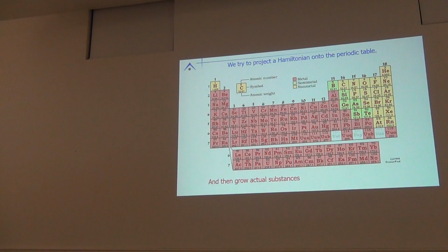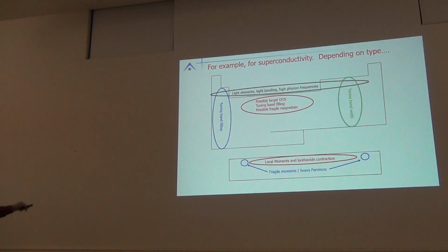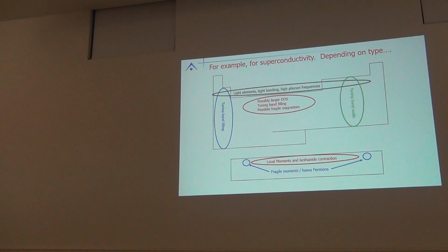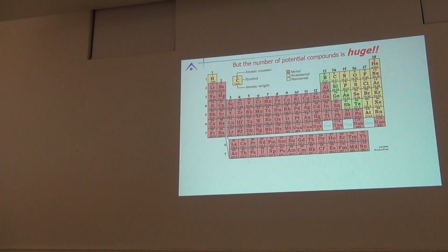We try to project a Hamiltonian onto the periodic table and actually grow substances. What do I mean by project a Hamiltonian onto a periodic table? Look, here's our periodic table, and if we think about this in terms of superconductors, light elements can give us tight bonding and high phonon frequencies. Transition metals can give us large density of states if we're thinking of a conventional superconductor, or possibility of tuning band filling or fragile magnetism if we have a non-conventional one. If we substitute alkali or alkaline earth for other valencies, this tunes band filling. By going up and down the chalcogenide or pnictide column, we can tune bandwidth. Here we can have fragile moments or heavy fermions. Here we have local moments. These are all terms in a Hamiltonian that let us try to control superconductivity. So we can use the periodic table to steer around the physical phase space.